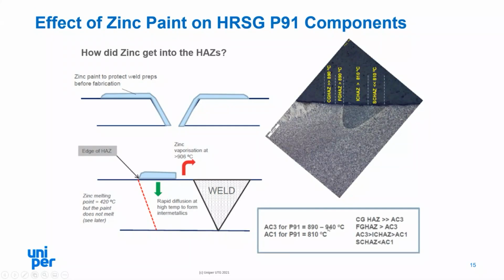Just to note there the AC3 and AC1 temperatures for the different zones, which you can see in the photograph here, highlights how you've got that temperature zone between about 800 degrees centigrade up towards 900, where we're seeing the diffusion. And it's also reflected in the very skewed bell-shaped curve that we're seeing here with the coating.